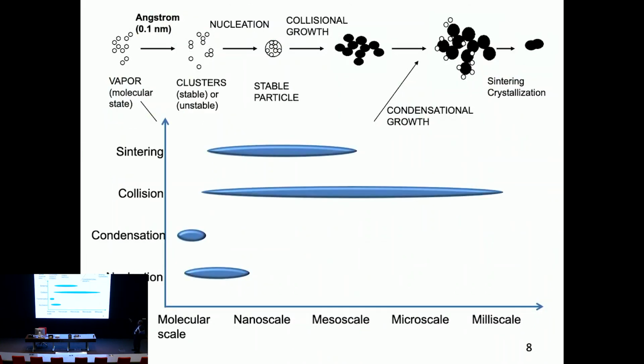Okay, so then I can show this. There are other mechanisms. Sintering is once I have collided my clusters, do they merge into a nice spherical shape and so forth. And I can cover multiple scales, starting with the molecular scale, of course, nano, meso, micro, even milli scale. So it's several orders of magnitude. The net to take from this is also, due to these processes, I'm going to get a distribution of particle sizes, right? And different concentrations. So the particle size might end up not being a single size, but a whole range of sizes and different concentrations that we really have to then account for.